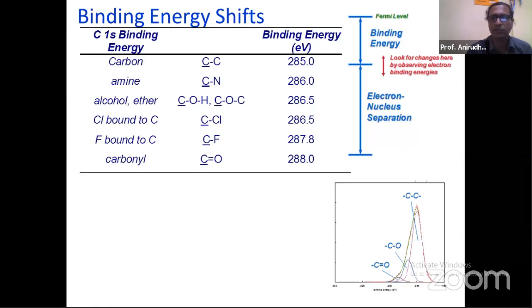People have done experiments to form bonds with carbon and chlorine, and they found that the binding energy for carbon in this particular coordination with chlorine is at a value of 286.5, which is different from its original value of 285.0. It is because of bonding that these electron energy levels are perturbed or disturbed, and they change to a new value. These new values are called shifts, and you can use this information on shifts in binding energies to correlate with the kind of bonding, using your information related to chemical bonding and your understanding of physics and chemistry.